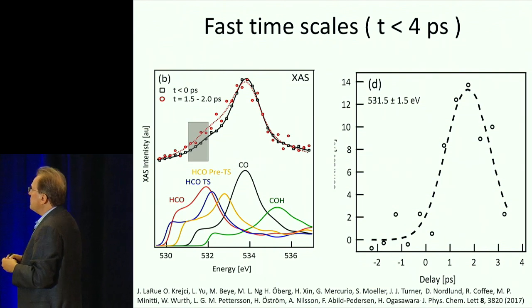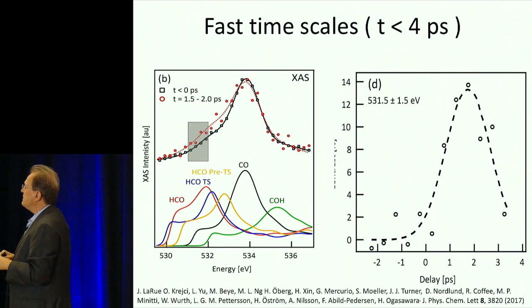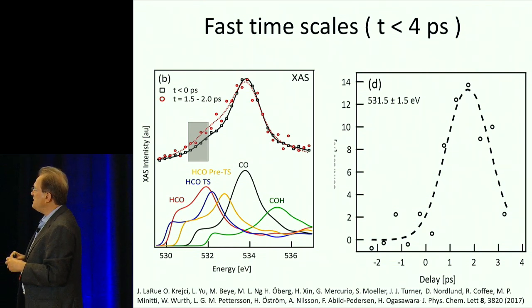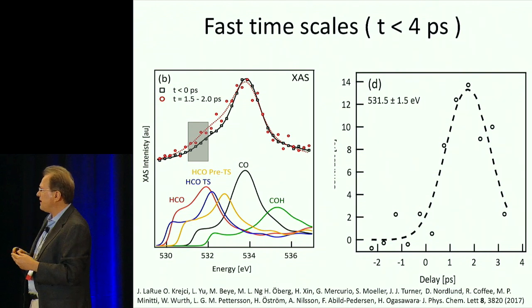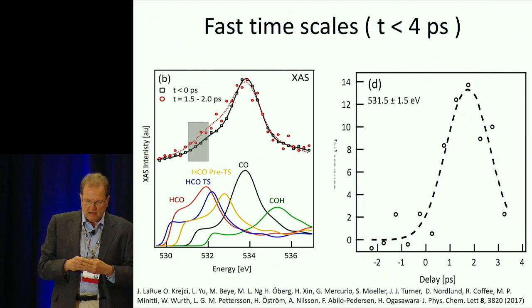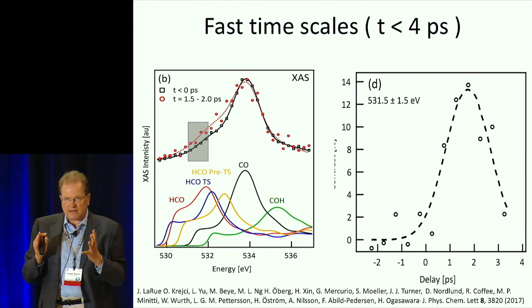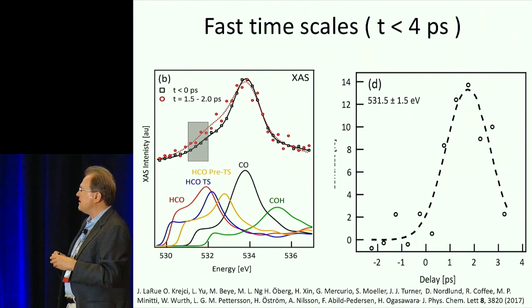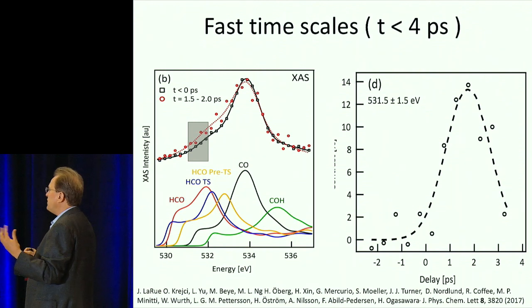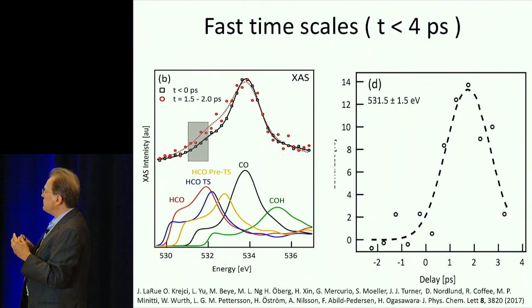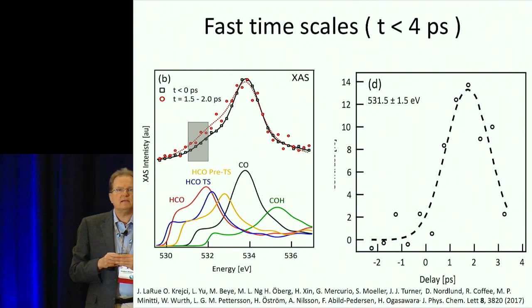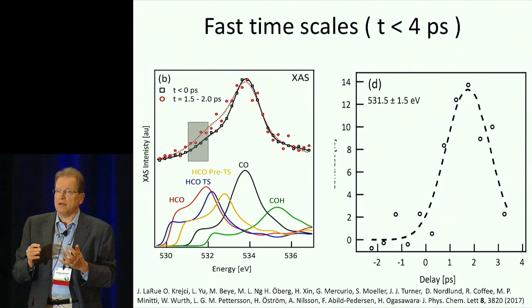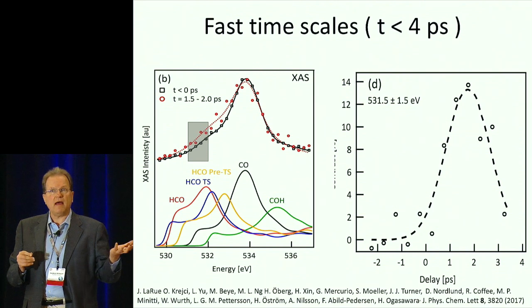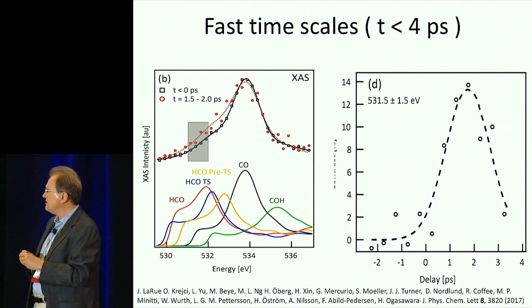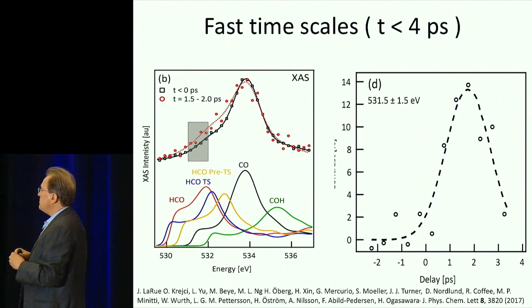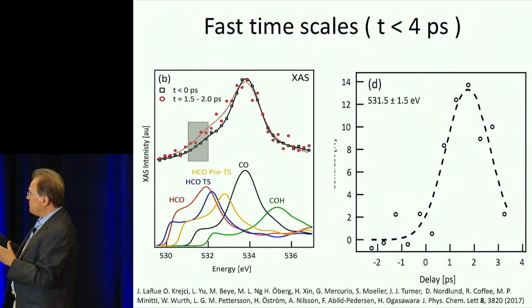As you are now looking at it after a few picoseconds, after you pump the system, you see that there is a tail, which is the red spectrum there, coming in, and it's marked there with a grayish color, where that intensity comes up. And we then ask ourselves, what is this intensity coming from? That's what you see in the lower part of the figure, which is simply a theoretical calculation of spectra that we have taken along the reaction pathway that was calculated. I will come to that in a minute. So you can see the CO species is well reproduced.